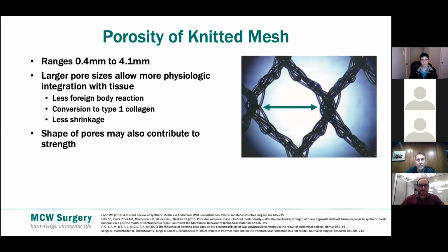So porosity of the knitted mesh, this is a pretty significant characteristic, in the range of the holes in these knitted meshes. The offerings tend to range from less than 0.5 millimeter to up to 4 millimeters. It's been shown that a larger pore size allows more physiologic integration with the tissue, and this creates less of a foreign body reaction within those holes and allows for a conversion to type 1 collagen, promoting a higher tensile strength as the tissue integrates. And with less foreign body reaction comes less contraction, which is also another adverse effect that we try to avoid. There also have been some studies that have shown that the shape of the pores may also contribute to the strength. So hexagonal shape was shown to have a higher tensile strength, but it was just a single study itself.